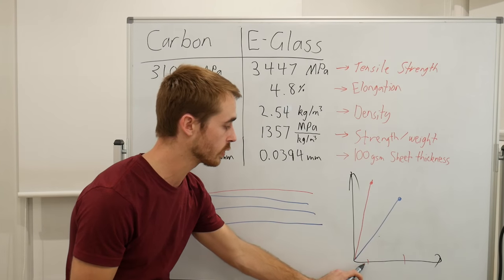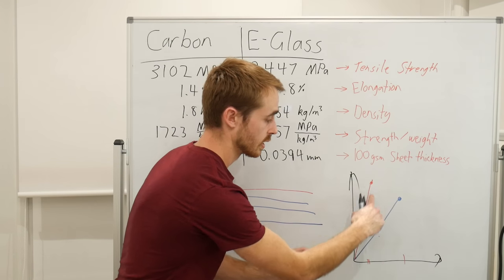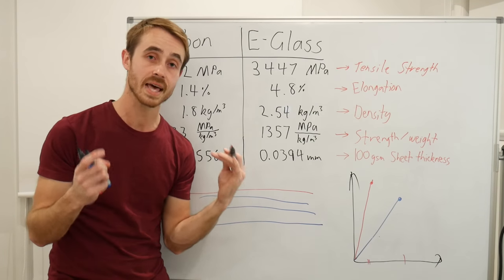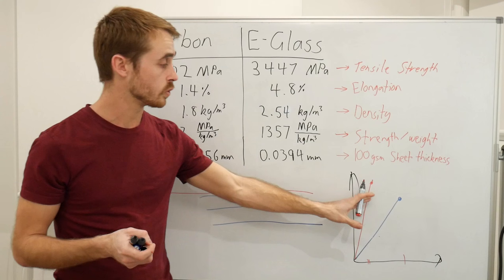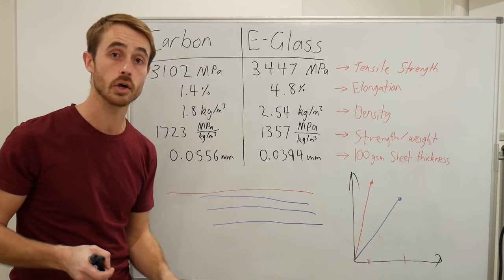As we move along and apply our force, we reach here, the carbon breaks and then the fiberglass has to take the load for the duration. That means your fiberglass, the second that carbon layer breaks, is taking 100% of the load.